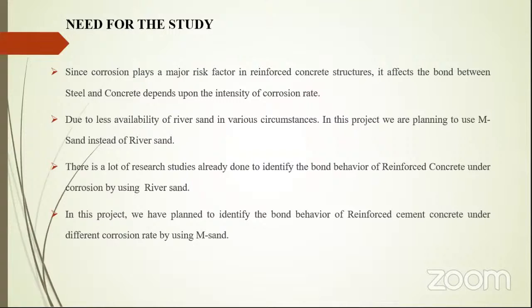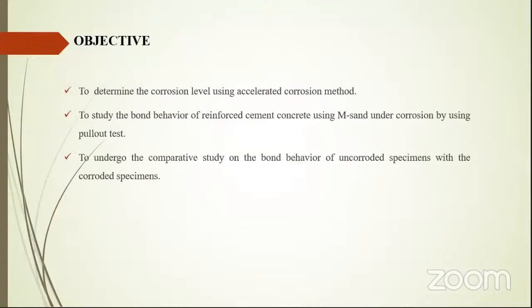steel and concrete depending upon the intensity of the corrosion rate. Nowadays the river sand availability is less, so in this project we used M sand as a replacement for river sand. A lot of research studies have already been done to identify the bond behavior of reinforced concrete under corrosion using river sand. Now we used M sand. The next objective of the project is to determine the corrosion level using the accelerated corrosion method to study the bond behavior of reinforced cement concrete using M sand under corrosion, using a pull-out test, to undergo a comparative study on the bond behavior of uncorroded specimens with the corroded specimens.